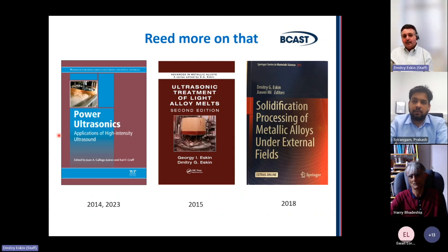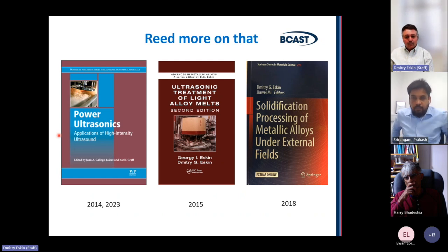And this is a technology which was developed, I would say, at least patented and developed on the level of modeling and some concept trials by University of Greenwich, group of Professor Pericleous, Koulis Pericleous. They suggested that you can use high frequency or superimposition of two high frequency electromagnetic fields to induce resonance in a volume of liquid metal. So in the center of the volume, you will have cavitation conditions.